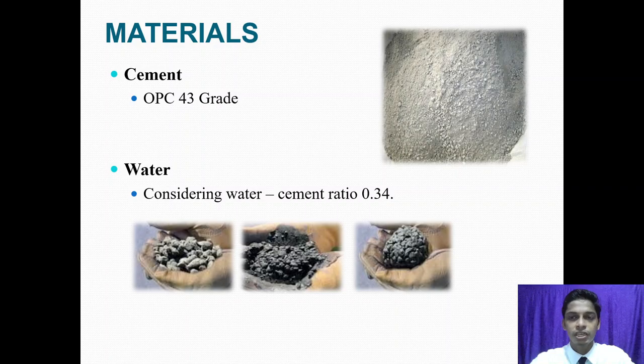Water. For strength characteristics point of view, water cement ratio is more important. For better strength, we consider 0.34 water cement ratio from journal. If water content is lower than the optimum, then the bond between aggregate cannot be achieved. If high, then the cement paste behaves as a fluid material and flows to the bottom of the pavement and blocks the pores and permeability.